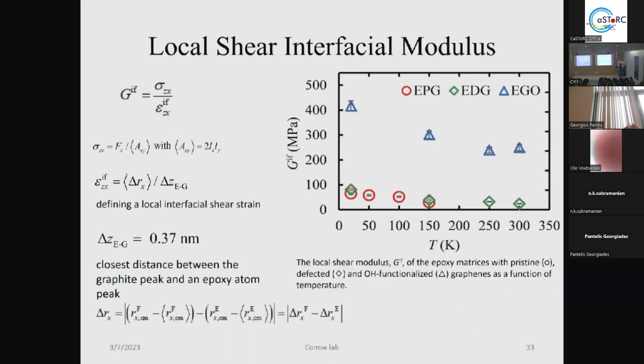The first thing that we were interested to see was an interfacial constant that the people doing experimental fracture mechanics, especially at macro scale, measure: the Winkler modulus, which is a modulus that explores the interface of two different systems. Usually one can find this constant in geomechanics or civil engineering systems.